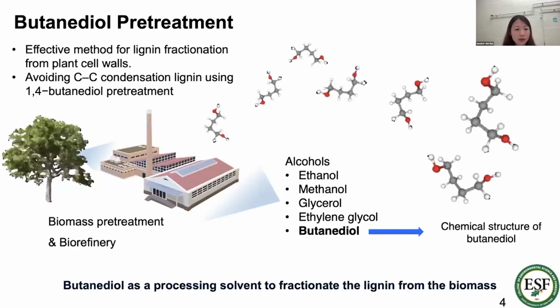As Dr. Bunjanovic introduced about the pretreatment methods to extract lignin, there are many effective ways to extract lignin from the plant cell wall, and many alcohols have been introduced to extract lignin from the biomass. So we can use ethanol, methanol, glycerol, ethylene glycol, and butanediol. We use butanediol as a biomass pretreatment because it is very effective at preventing the condensation of lignin, which means this extracted lignin preserves the structure of lignin well compared to other pretreatment methods.